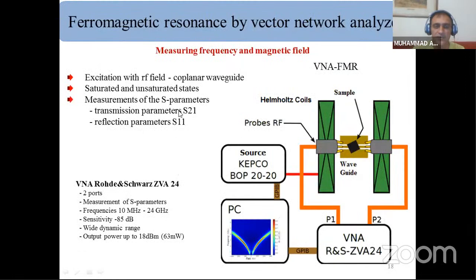Ferromagnetic resonance. With the help of VNA FMR, we can explore the magnetization dynamics of our magnetic system. This VNA FMR consists of a waveguide here. The sample is placed on the waveguide. For the AC field, we apply an AC field through this central conductor, through the VNA, and the DC or sweeping field which is required, we apply through a magnet. This is the source of the DC field. We apply a DC field to the waveguide.